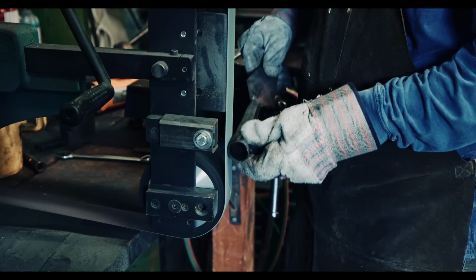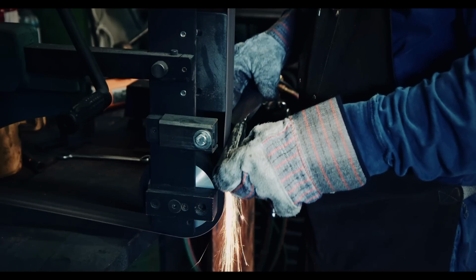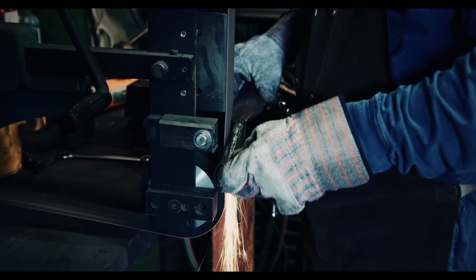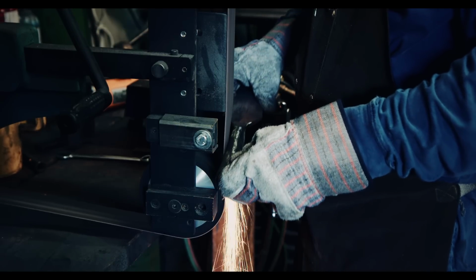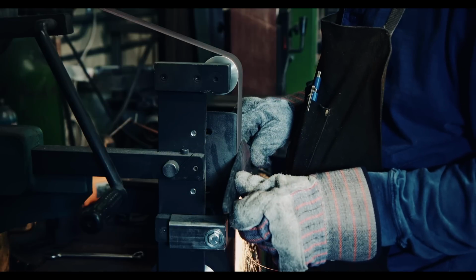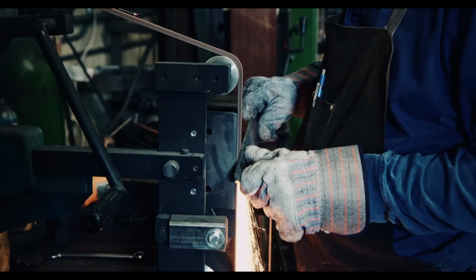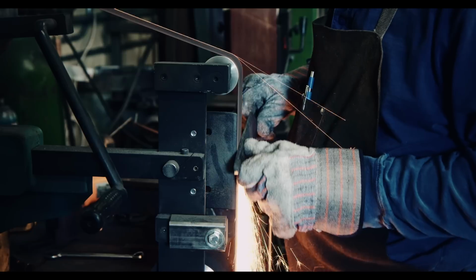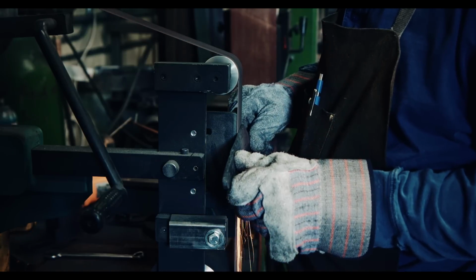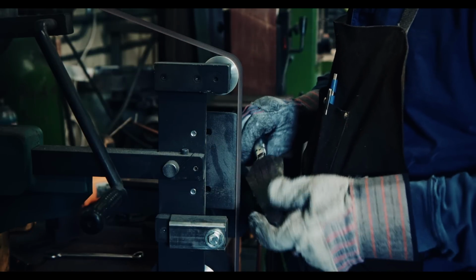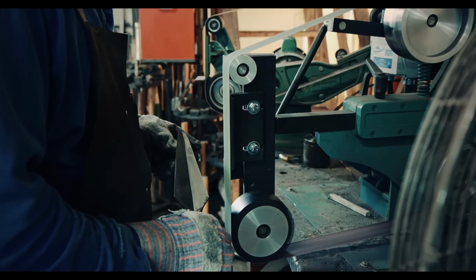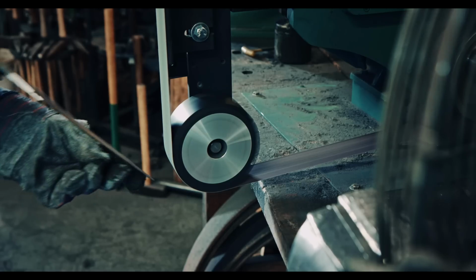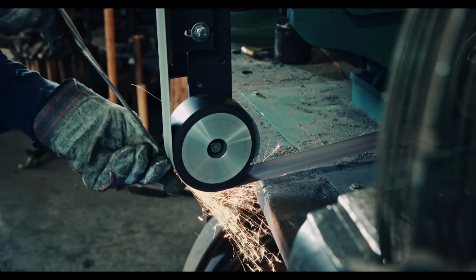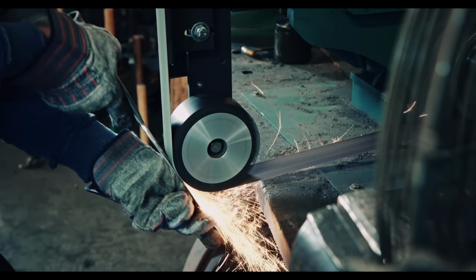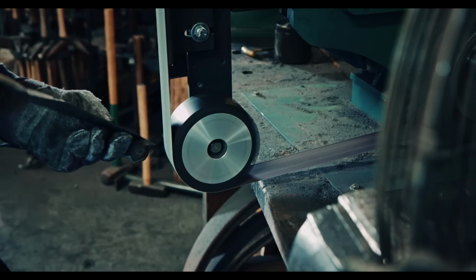Finally, all forging has been completed, and it's on to the grinder to remove all scale and prepare the spear for heat treating. You may notice that I'm grinding the blade on the platen. I need to be very careful to not remove too much thickness from the spine, and probably would be better off grinding a concave profile on a big grinding wheel. Whenever I heat treat, I'm trying to remove any vertical grinder marks since they might lead to cracks when quenching.